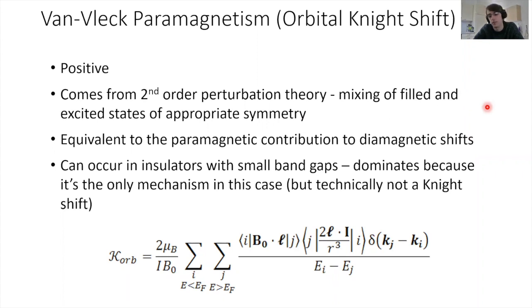but this is the same thing as the paramagnetic contribution to diamagnetic shifts, for those who are familiar with that. And it comes from mixing filled and empty states. You can see this coming about via second order perturbation theory. And this always ends up with a positive shift. And put simply, it's weighted by the energy difference of your filled and empty states, and terms involving their symmetry results in a shift.